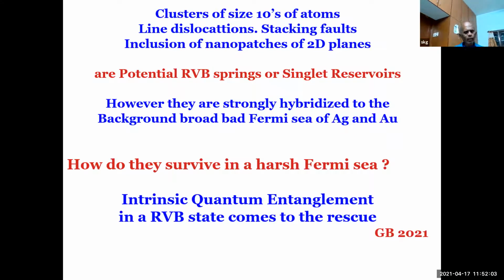So what did I do? I hypothesized that clusters of size 10 of atoms, line dislocations and inclusions are potential RVB springs for a singlet reservoir. Because theory tells me and experiments tell me that if I have isolated clusters or isolated chains, they definitely have very strong above room temperature local TC. But they cannot support long range phase order for various reasons.